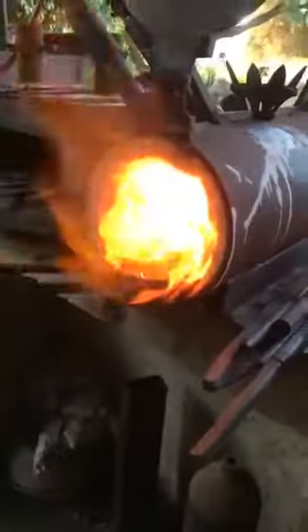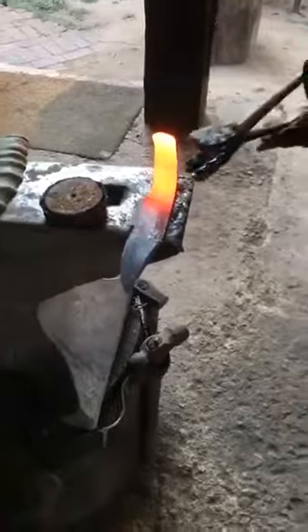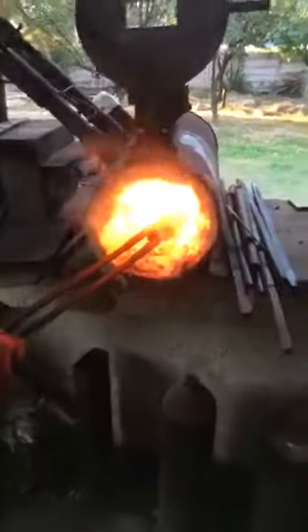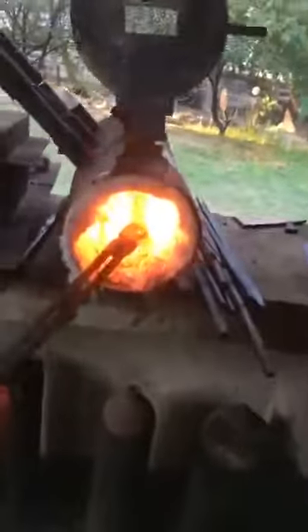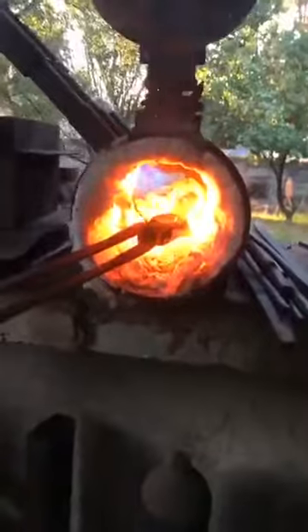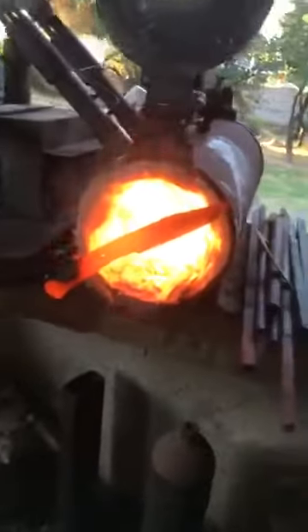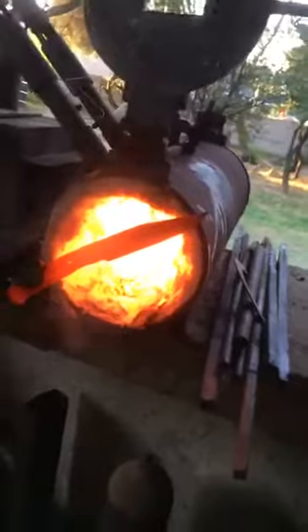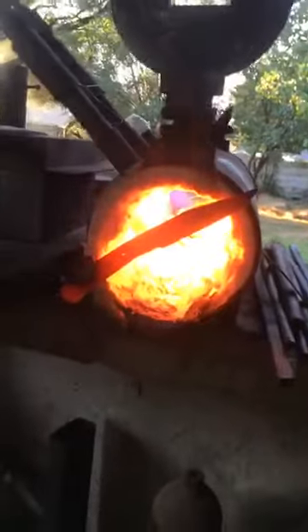Right, so that blade's looking nice and warm on the handle. So let's turn them around. Grab it from that profile so I can get it into the oil. So as deep in as possible now. I've got 2 burners on this forge, so it's past the second burner. So you can see that shadow in there. We want that shadow gone. And I don't want the tip or the edge to get too hot. So you can actually just let it soak a bit here in front of the forge and just get some heat in from the back.